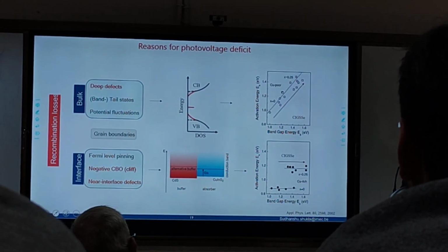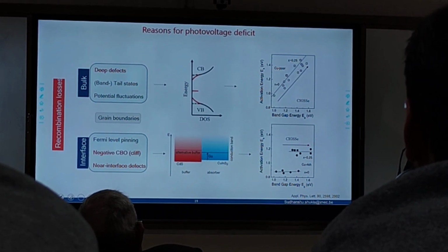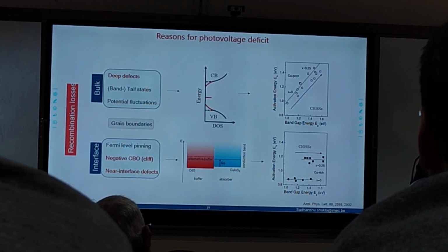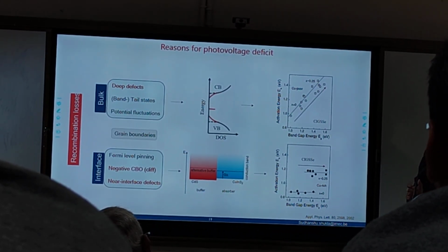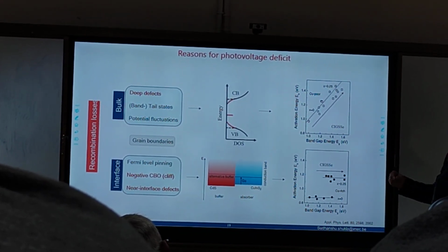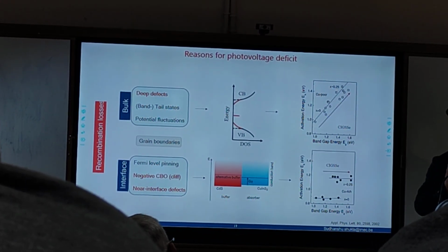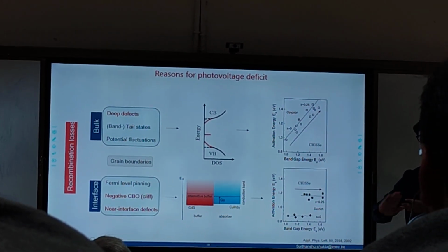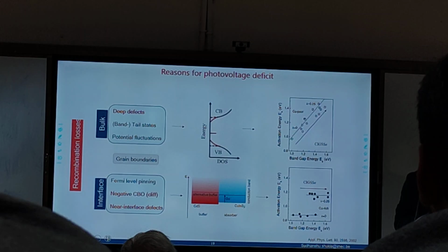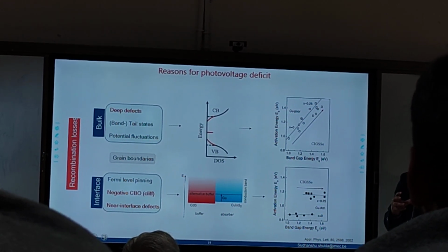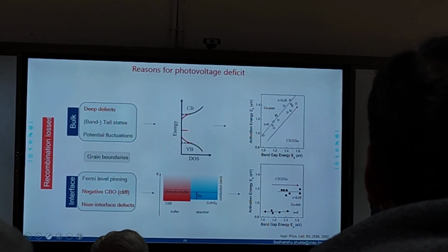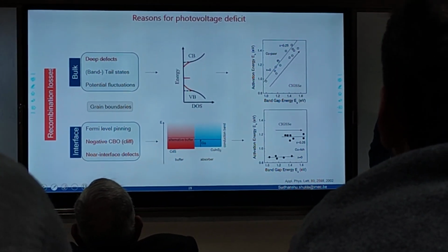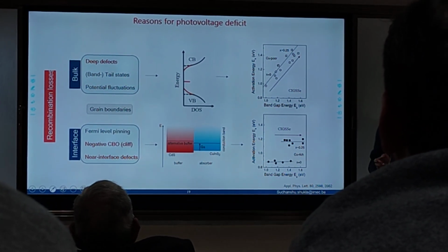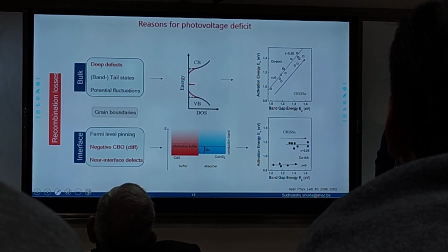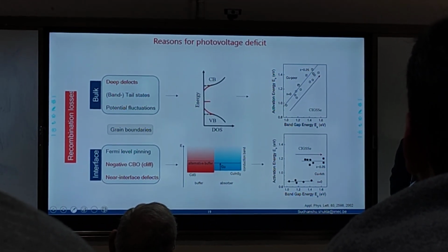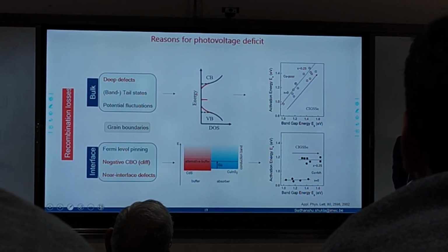These defects are inbuilt or you induce the defect? Some defects are intrinsic, spontaneously formed because of the virtue of their formation energies, which you can actually passivate by changing the growth conditions. And interface defects also form because of the way you make the contact with other material. You can passivate them by putting some sort of a passivation molecule or something. Yes. Sometimes you have extrinsic defects. Let's say you did synthesis, but you have chlorine or something coming from somewhere, like a crucible can be a source of aluminum, and that aluminum is doping and making it crazy. These are long stories, but we have less time to talk about. But this has happened in the literature. There's a Nature and Science paper talking about good performance, and all that was coming from the crucible.